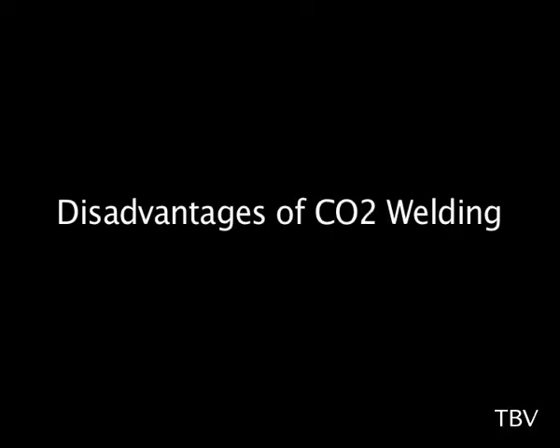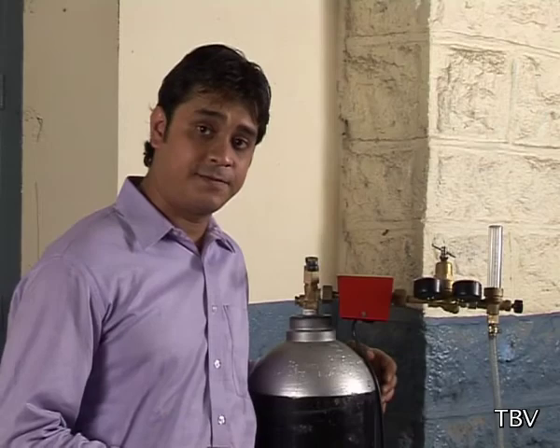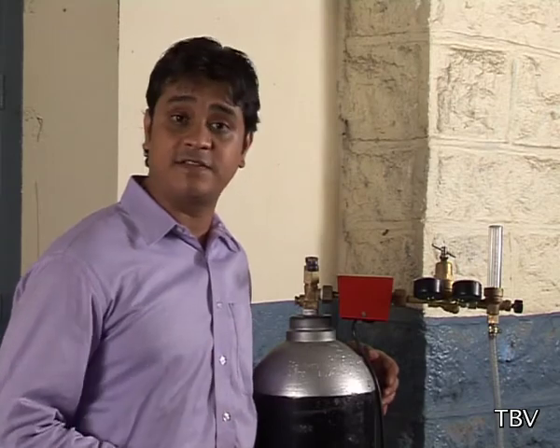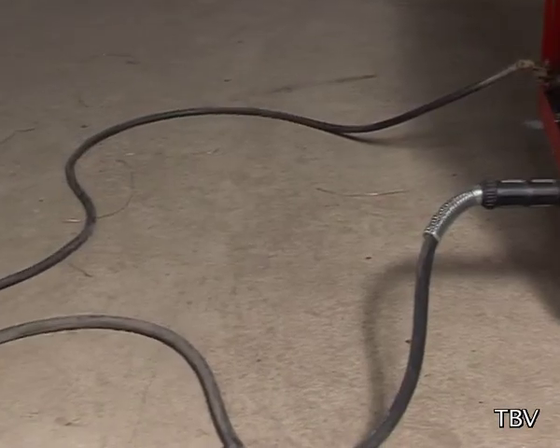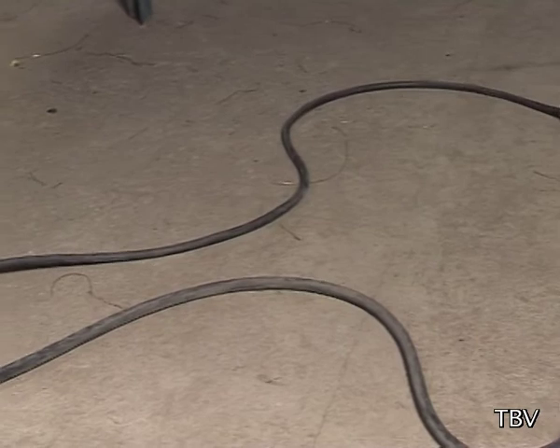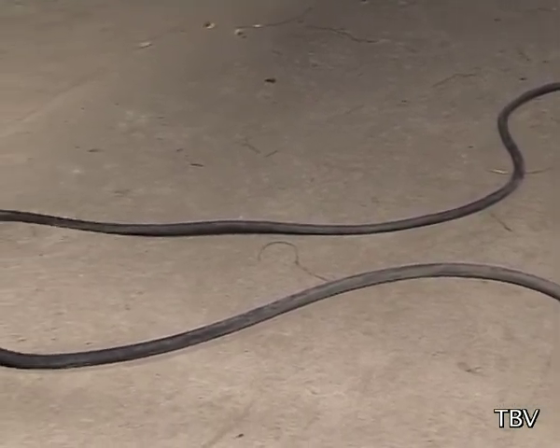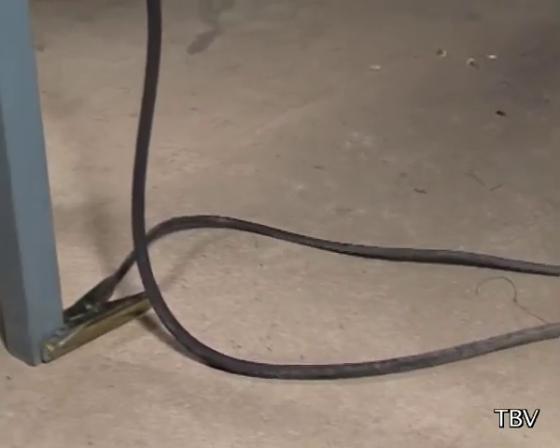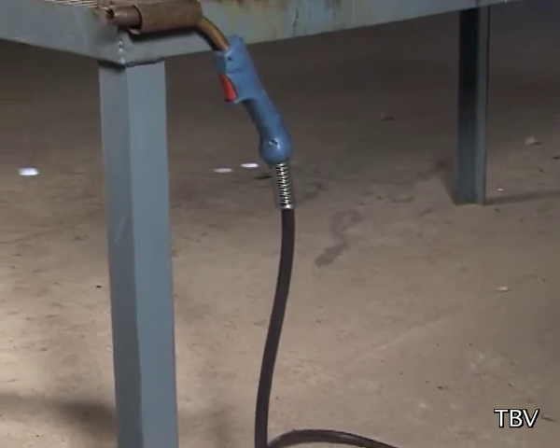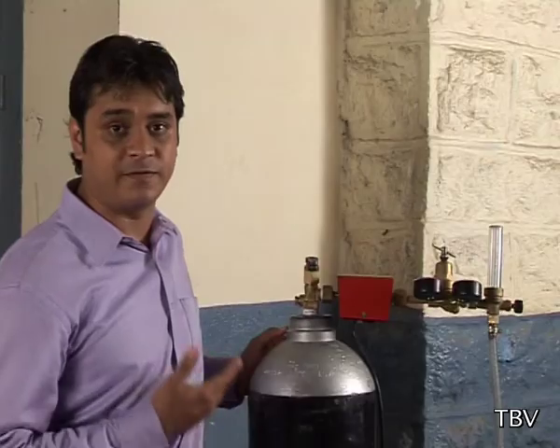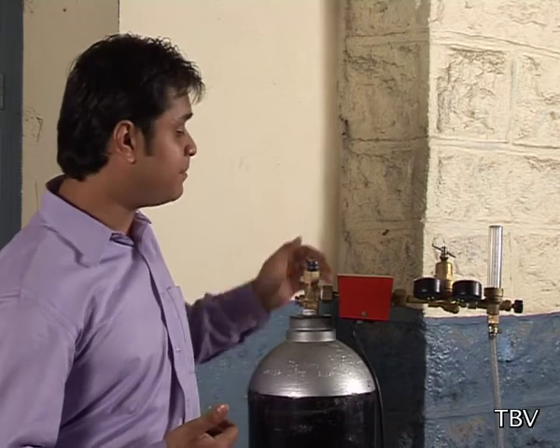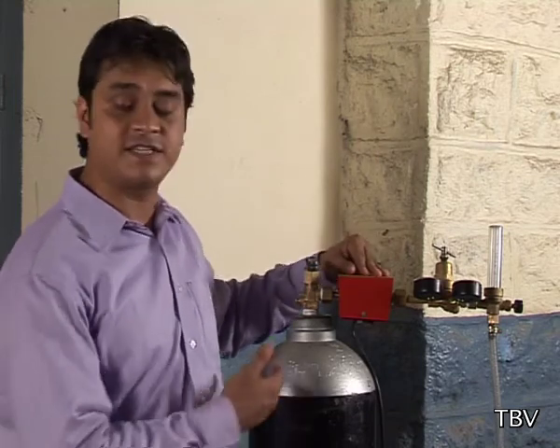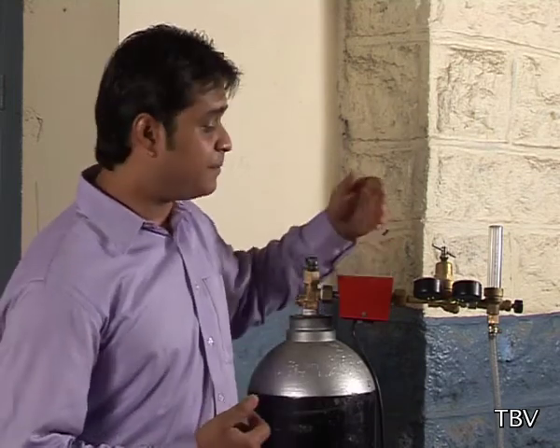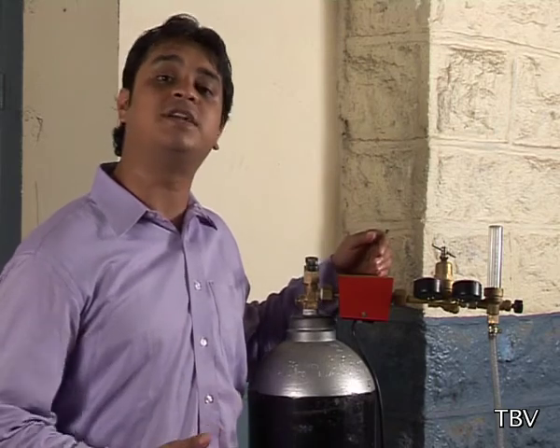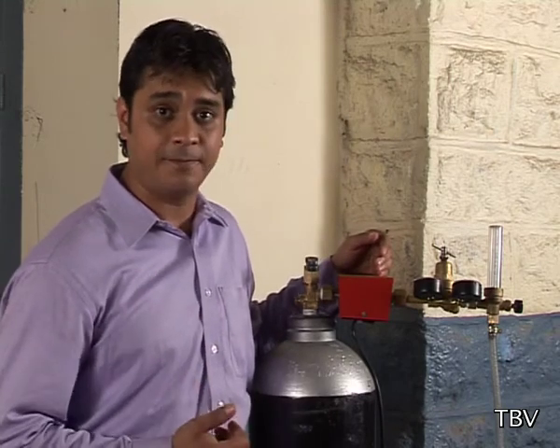The main disadvantage of CO2 welding is the cost. The equipment is very expensive, complicated and less portable. The welding can only be done within a certain distance from the machine. This is because CO2 is stored in a cylinder in liquid form. It needs to be converted to gas before it is used, and that is done by passing it through a gas heater which is attached to the cylinder. If the pipe is too long, the CO2 will turn back into liquid form quickly.